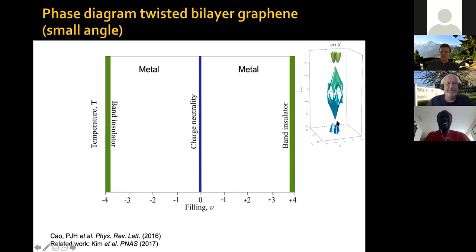The same thing if you fill with 4 holes, if you empty completely this band and you have 4 holes per Moiré unit cell, you also have a band insulator. And then you have also the charge neutrality point and metallic behavior in between. Okay, this is for small angle twisted bilayer graphene, but not yet magic.